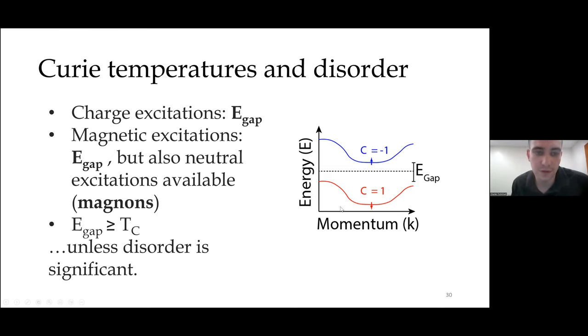So the magnetic degrees of freedom also have access to magnons. The spins can cant, which generally costs less energy than promoting an electron from the valence band to the conduction band. And that means that generally speaking, you expect the energy scale of magnetic excitations, something like the Curie temperature or the Néel temperature for an antiferromagnet, to be smaller than the energy scale of the charge gap. And this is something that is easy to probe in an experiment and is very sensitive to disorder. So if you have a situation where the local Fermi level is varying a lot as a function of position in the device, that will only reduce the charge gap without reducing the Curie temperature.